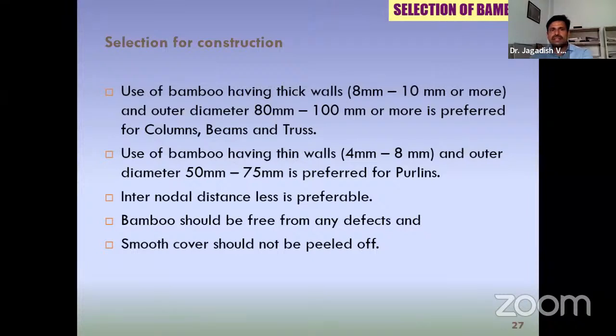For various elements, you have to use different thickness and different diameter of bamboo. Typically, 75 to 100 mm, that is 3 inch to 4 inch diameter bamboo, we take. And a minimum of 10 mm wall thickness we consider for either columns, beams, or trusses. Typically, the bamboo is tapered in nature from bottom to top.